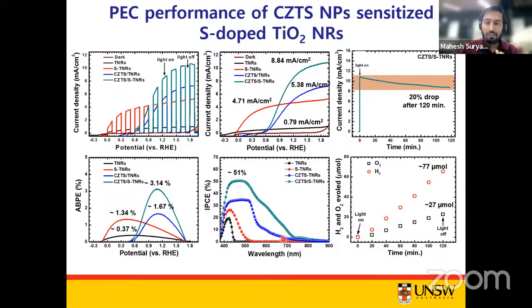We also measured the H2 and O2 evolution performance, which shows a value of about 77 micromole after about 2 hours of water splitting reactions. However, if you look at the stability plot, you can clearly see that there is a 20% decrement in the initial photocurrent density value after the CZTS sensitization on the sulfur doped TiO2 nanorod arrays.